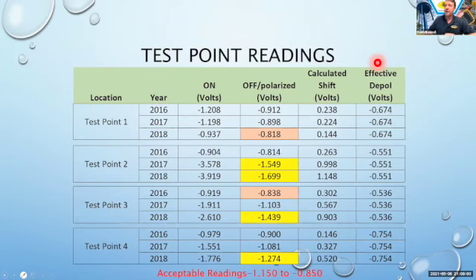Ideally, when you experience a situation where your polarized potential is less negative than your 0.85, at that time is when you should go through and do some additional testing and depolarize your system, turn those rectifiers and impressed current systems off, and come up with a new effective depolarized potential to compare. The concern is, conditions can change. This depolarized potential could change through time. So a more prudent effort on their part to really utilize that 100 millivolt criteria, I think, is the point to be made here.